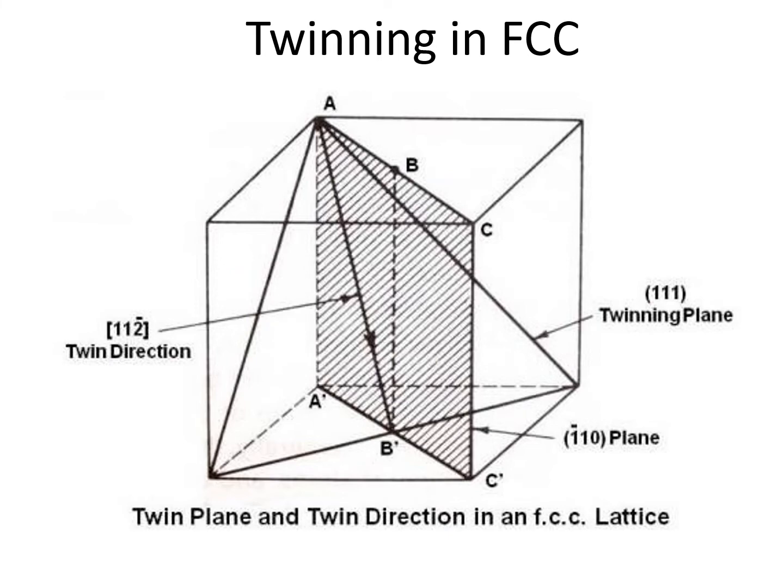And this formally is what describes a twin operation. We have a twinning plane. You have a shear on that plane and all the successive planes above it. But there is an invariant plane, which is this one, which is common both to the base crystal and the crystal that's sheared. So they share this one invariant plane, which is in the direction of the shear. And they also share a common plane, which is this twinning plane. But for all other directions and planes, they're different.